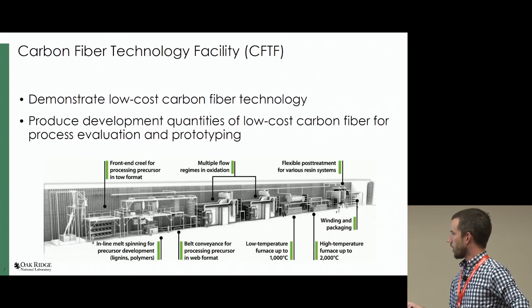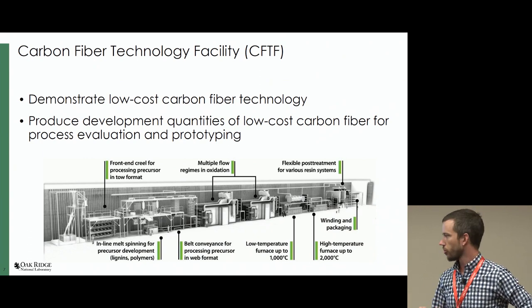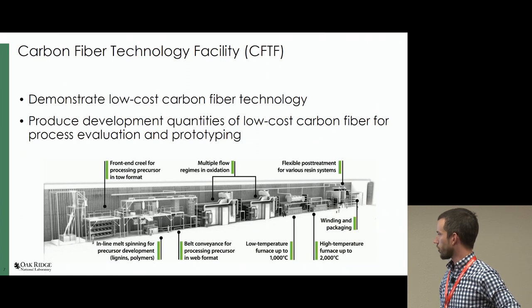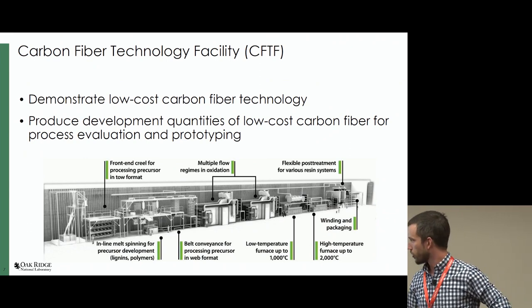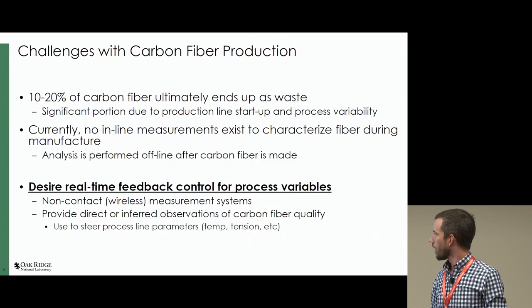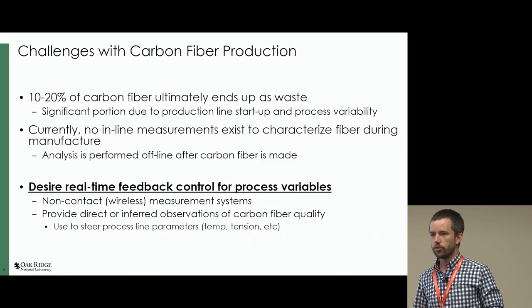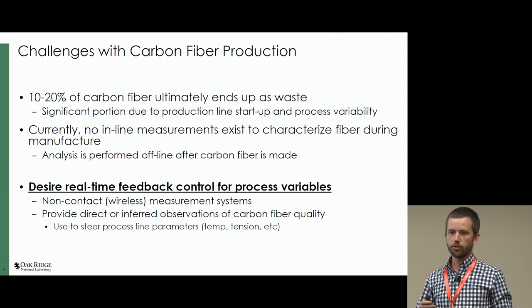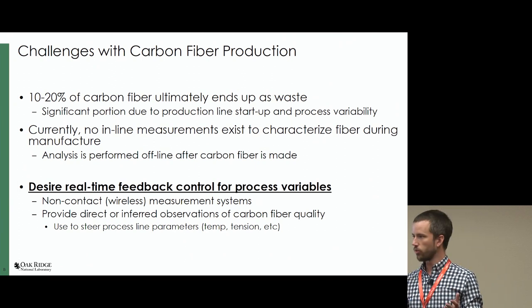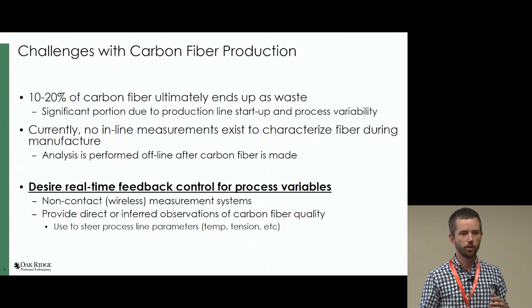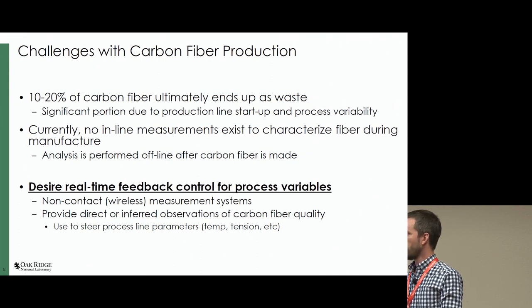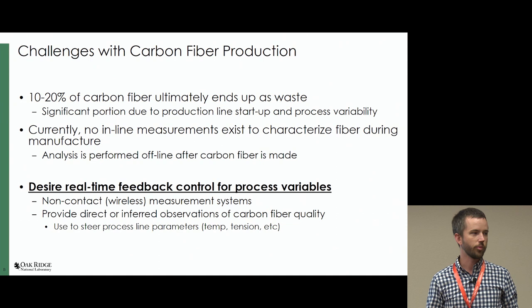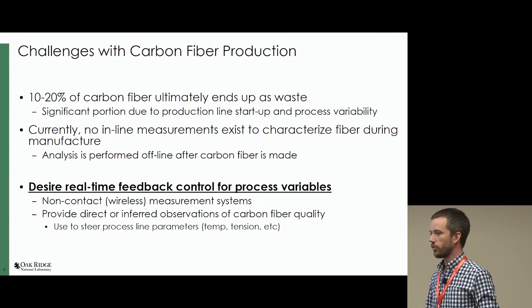At various points, the fiber will have different material properties. We're interested in the point right after the oxidation furnaces where the conductivity really changes, so you can see something show up on a microwave-type measurement. A lot of carbon fiber material is wasted every year — 10 to 20% is just lost. It goes through this whole conversion process, and at the end they take the carbon fiber to the lab and measure it. If it doesn't meet specifications, they throw it all away. It takes about 24 hours from start to finish to get to the point where they can measure it.